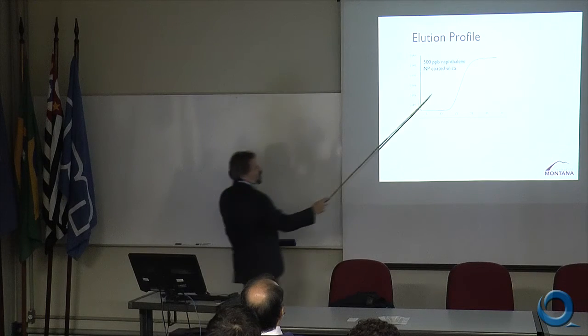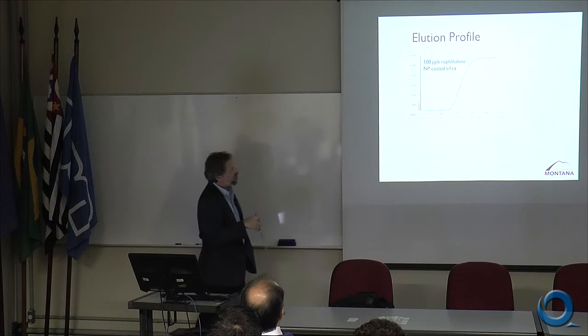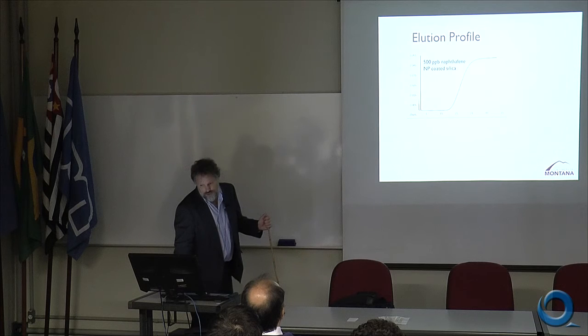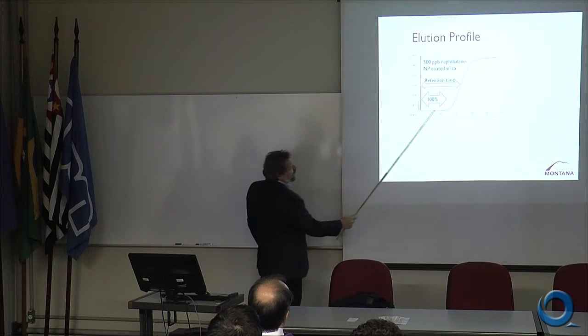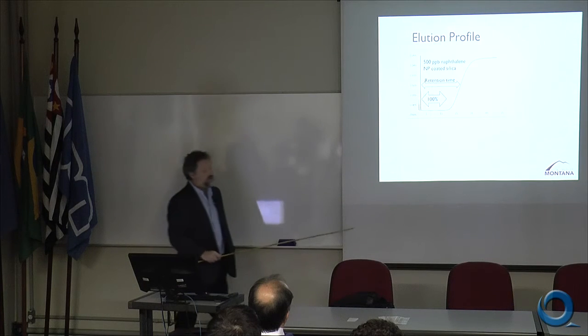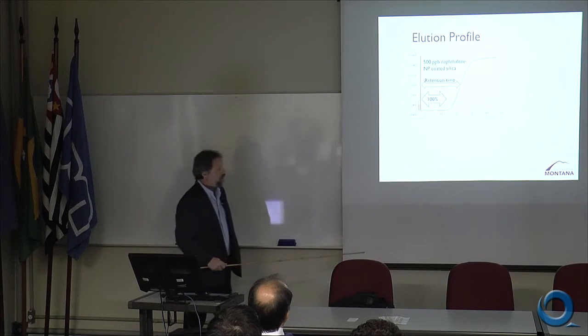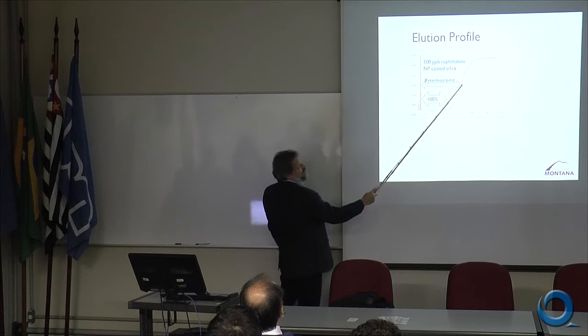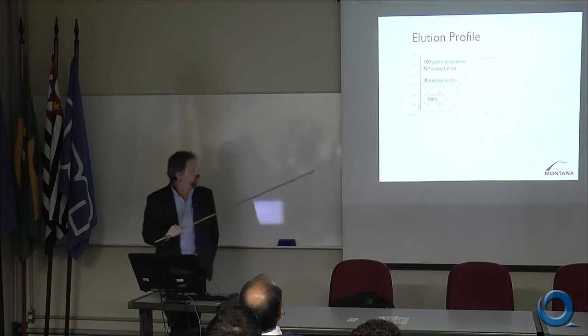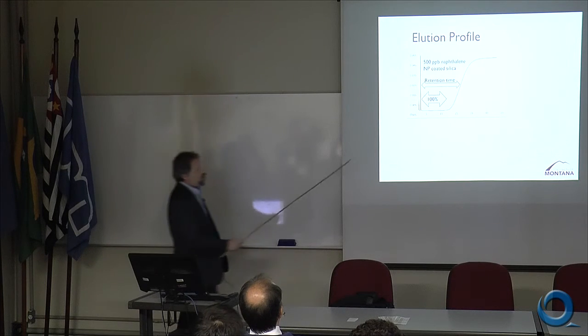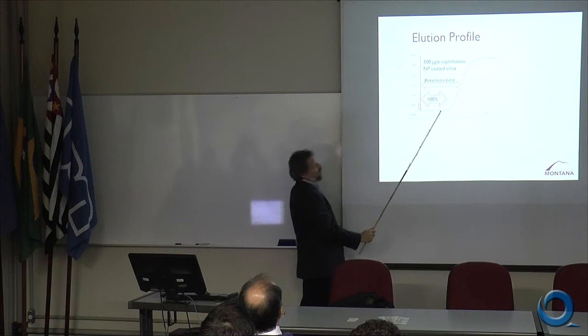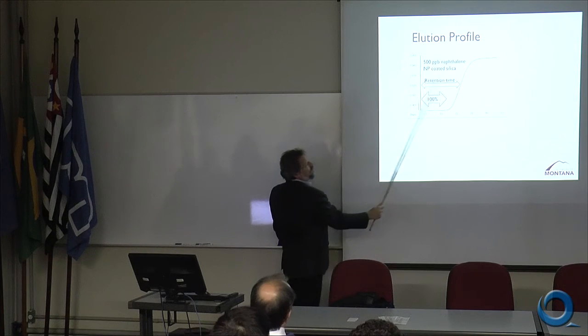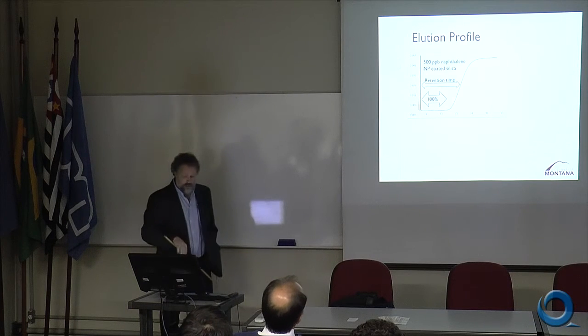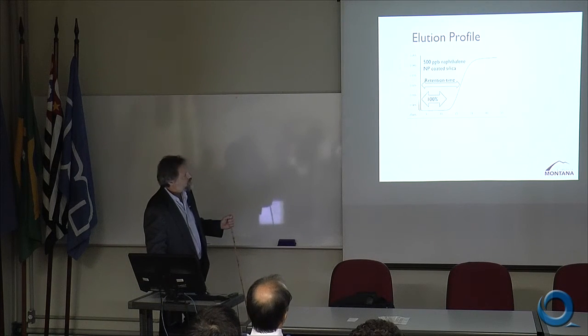And it goes up and eventually will stabilize at the maximum concentration. This is the signal you would get for 500 ppb naphthalene. So if you were using this in a solid phase extraction system, it's this region here where you would be able to get 100% recovery because none of the naphthalene has started to break through yet. And if you think about this in terms of standard chromatography, this would be our retention time here to the inflection point of this elution front. And this retention time does not change with concentration. The maximum signal here changes with concentration, but this time zone here, as long as we're working within the linear region of the chromatography, does not change.